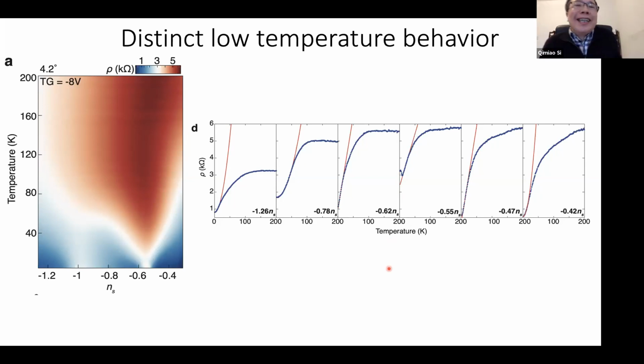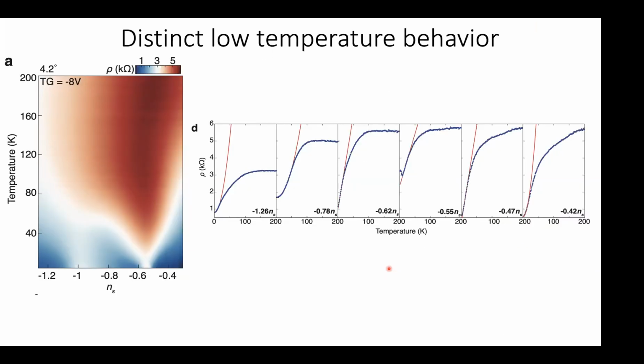So the magnetism might onset perhaps before the transition. Well, we see that in the bulk materials all the time. Sure, that's certainly possible. Good, very good. Thanks. But if you believe there's magnetism, that the resistivity goes up at the metal insulator transition, isn't it that in a Mott insulator you expect the gap opening at very, very high temperature? Kenshi, you are jumping the gun, right?